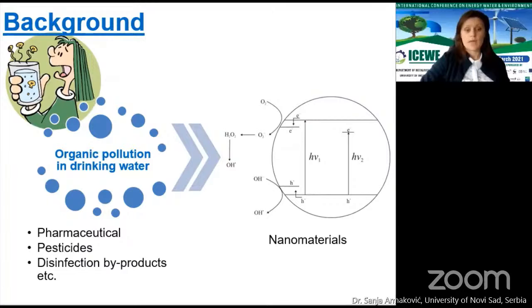An effective way to deal with this problem is the degradation of the drug by advanced oxidation processes, based on the formation of hydroxyl and other radicals. Many advantages of titanium dioxide over the broad range of other nanomaterials have led to the situation where titanium dioxide is one of the most frequently employed photocatalytic materials. Many organic substances and their intermediates are in this way completely mineralized.